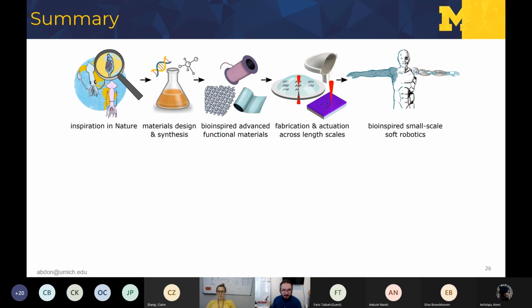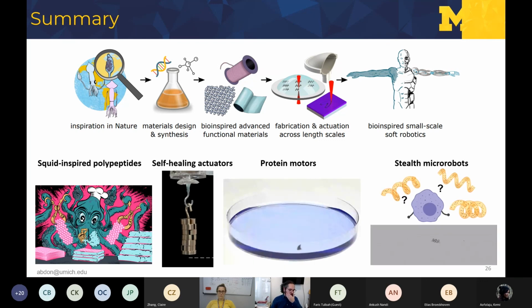So what we have seen today is that we developed these squid-inspired polypeptides that have an optimized network topology, a network structure with beta sheet physical crosslinks that have very fast and strong self-healing properties by the formation of this nanocrystalline structure. And we used it to develop these self-healing actuators for both pneumatic but also magnetic actuation that can not only enhance their durability but also enable new functions and new modularity in their actuation modes.